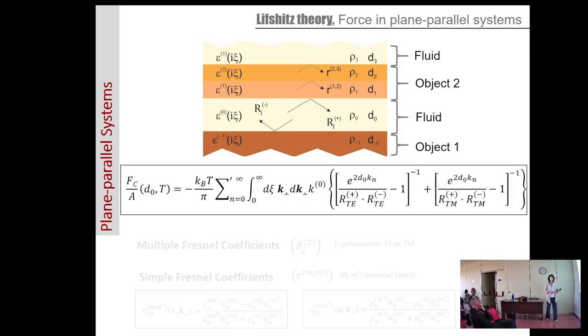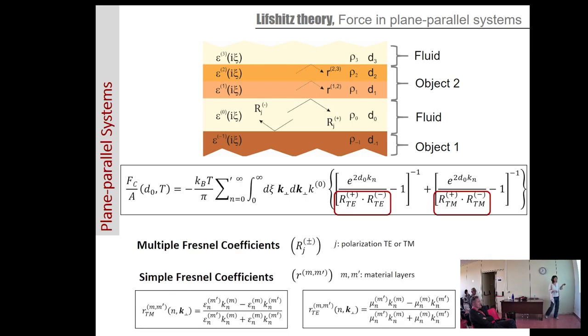How do we calculate the Casimir force for a multilayer system? So we have any general multilayer system where we have an object, then we have another object, it can be just one film or bilayer, multilayers, whatever, all immersed in a fluid. So the Casimir force per unit area at a finite temperature is given by this expression here. It could be more or less complicated, but we can identify here the multiple Fresnel coefficients of the bottom and the top surfaces in this fluid, which in turn depend on the simple Fresnel coefficients. And this is where the permittivity of our material is entering the equation.